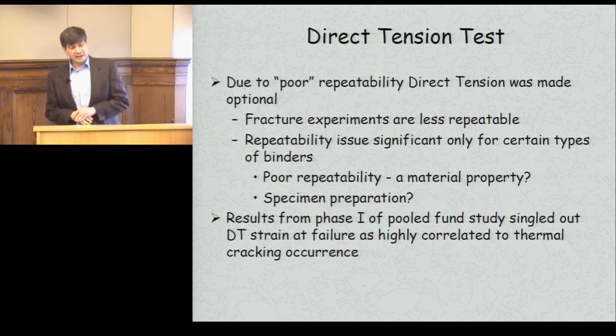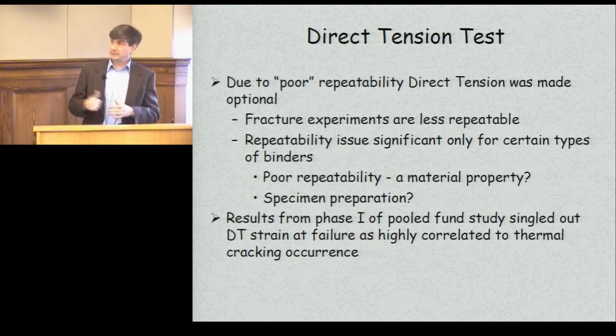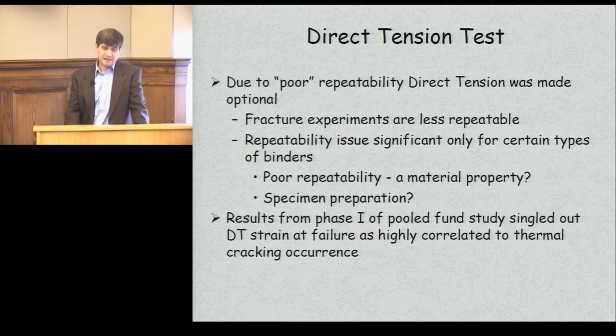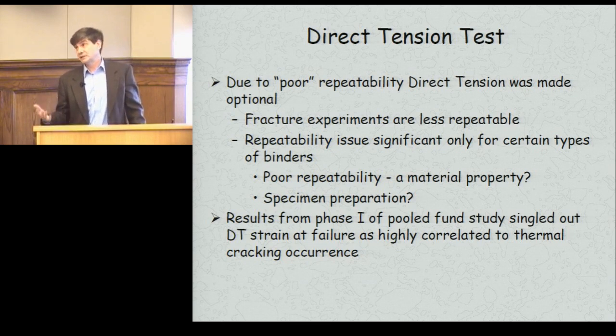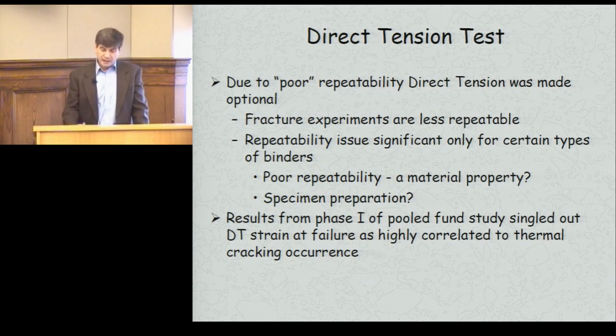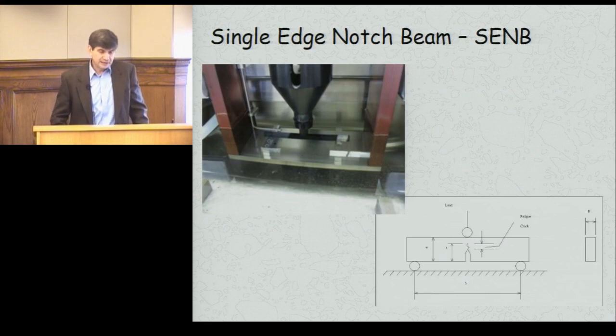And as a matter of fact, our research as part of the first pooled fund study that I'm going to mention in a second found out that exactly the parameters, actually the strain at failure at low temperature, was the one that correlated best with cracking in the field, which really tells you that stiffness is not brittleness. You really need a fracture type parameter if you really want to go in a serious way after what makes pavement cracks.